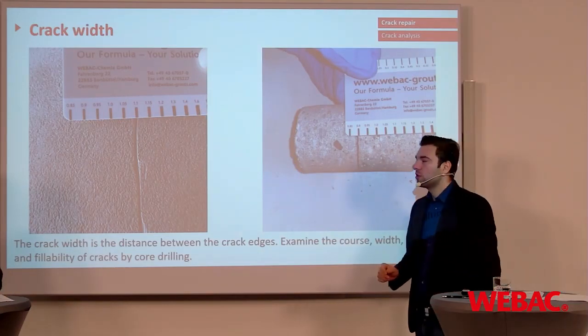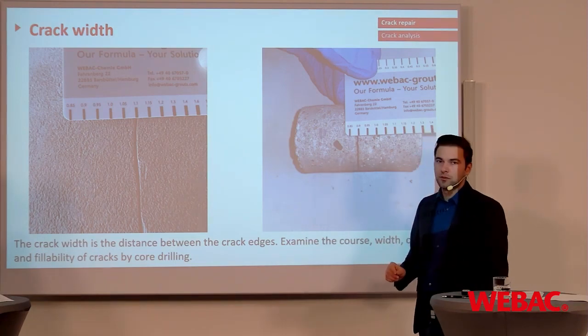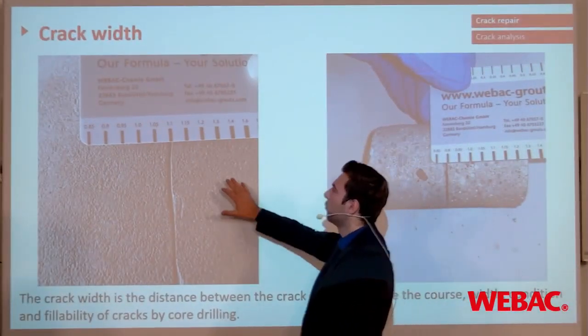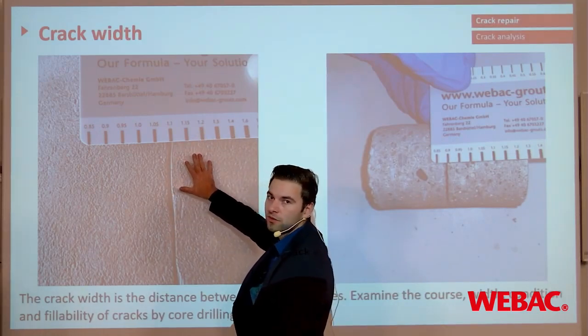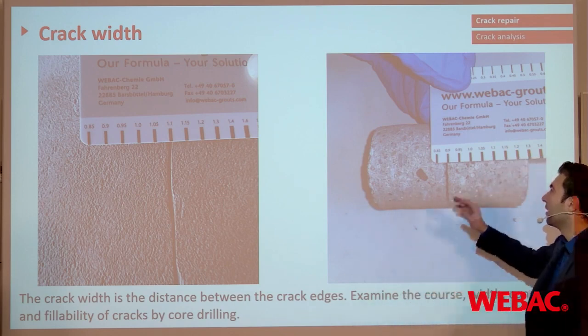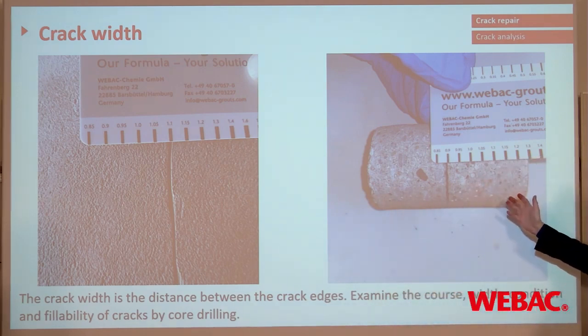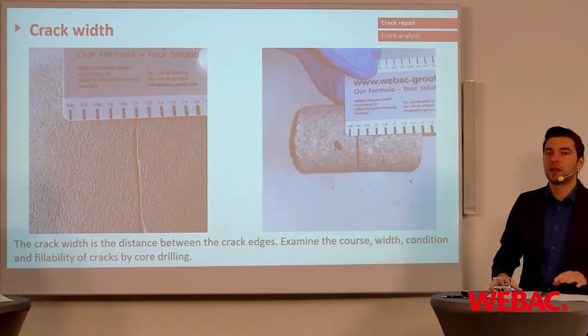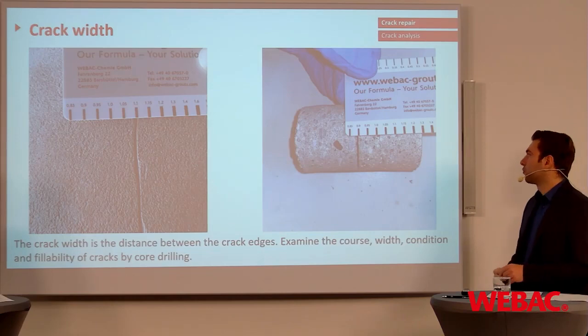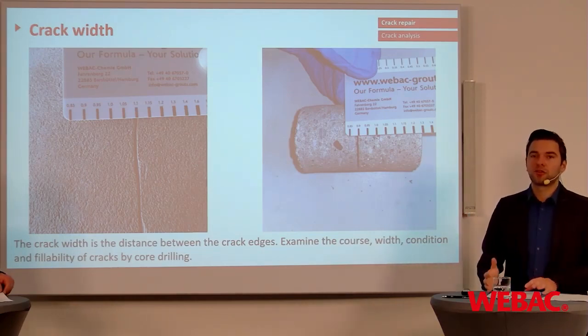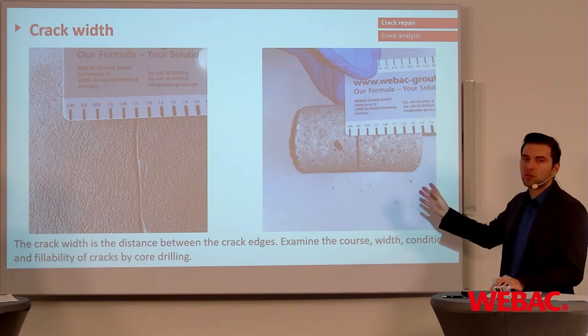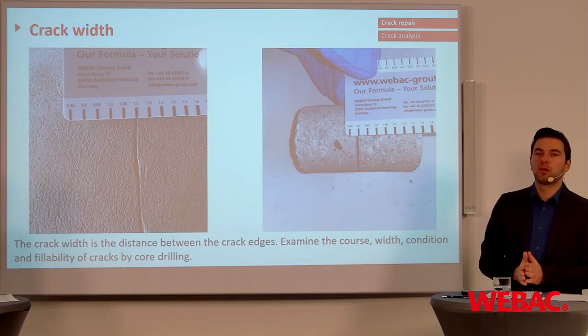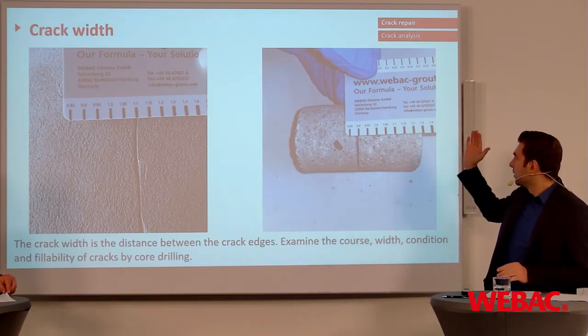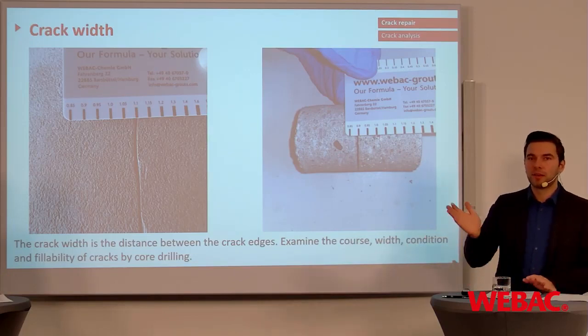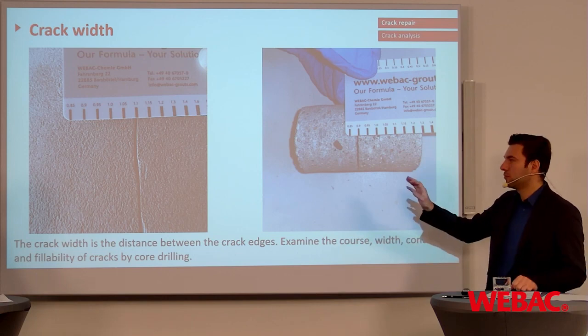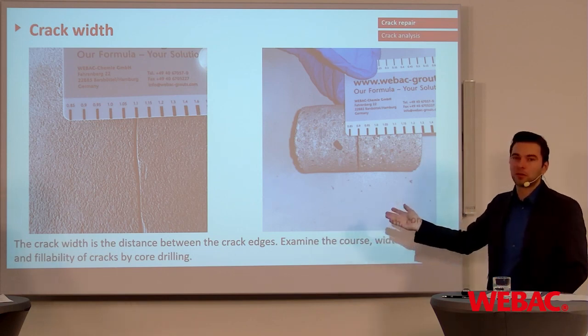It is very important to measure the crack widths prior to the injection, and there are two ways of doing it. You can simply measure with a crack scale the width of your concrete on the surface. The other option, which is not more complicated, but you have to do further work, is just to take out a core drilling. And this core drilling for sure gives you a better feeling and understanding of how the crack is going in your structure. Is there any change in the crack width? Is it smaller, thinner? Is it wider? Is it an even crack in the concrete? Are there pathways? These are things that you cannot see from the surface, and therefore you would have to take out the core drilling.